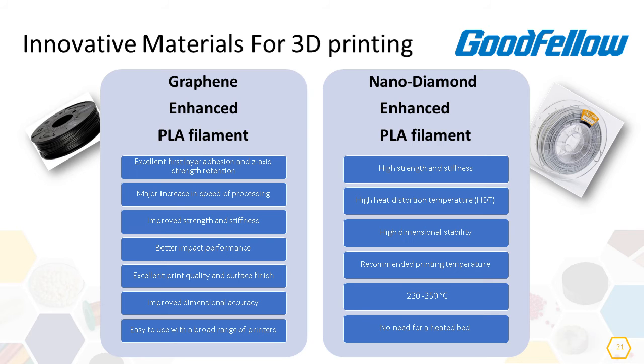While sustainability is of great interest and a challenge for all research and engineering areas, Goodfellow combines these emerging technologies and is offering two 3D filament composites. One filament is PLA, or polylactic acid, enhanced with graphene, demonstrating enhanced properties such as strength, thermal conductivity, anti-static behavior, and dimensional stability. And the other filament is PLA enhanced with spherical nanodiamonds, offering high thermal conductivity. Although the nanodiamonds are spherical, this filler is less abrasive than other fillers generally used in composites for 3D printing filaments, because the other filaments in general have irregularly shaped fillers.